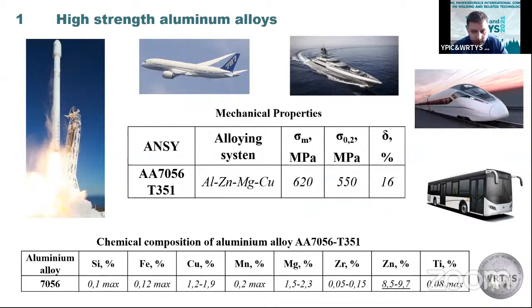They belong to the group of hard to weld or non-weldable aluminum alloys. At the same time, at present, a technological process such as riveting is used, but riveting is very laborious, economically demanding, and an operation associated with difficult working conditions. We need to make a very careful surface treatment of the rivet hole for a reliable connection of the product, and during long-term operation, the riveted joints are susceptible to loosening, which affects the service life of the products.